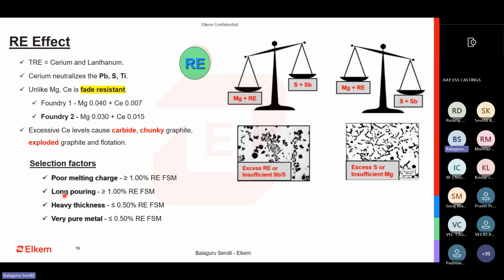And when you're having long pouring, you don't have the problem of having poor melting charge. I have decent charge. I don't have that much of trace elements, but I'm operating at 0.025, 0.03 residual magnesium. And my sulfur is about 0.010 in final, but still I'm having fading because my pouring is quite long. Then I would suggest, instead of increasing the FSM addition or going for a higher grade of magnesium, I would use the same grade of magnesium, preferably at a lower addition rate, and have the rare earth in the FSM increased from 0.5 to 1, from 1 to 2.